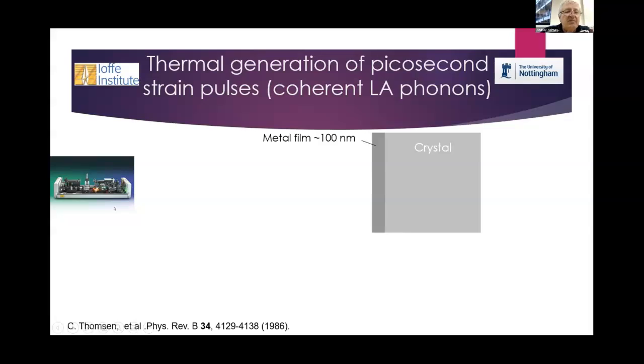We excite it with a laser pulse. It hits the film, which expands, and this happens quite quickly, injecting a strain pulse into the crystal. This is all known from the 80s.